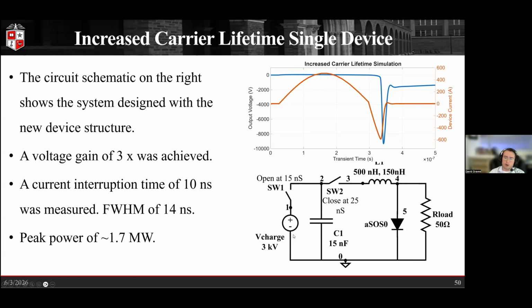So in this figure, we're charging to 3 kV. This is the circuit used, very similar structure, just different values. So now we're using 15 nanofarads. We're using 500 nanohenries in forward pumping and 150 nanohenries in reverse pumping. And we're able to get a voltage gain of 3x, meaning the single device gives us a 9 kV pulse.